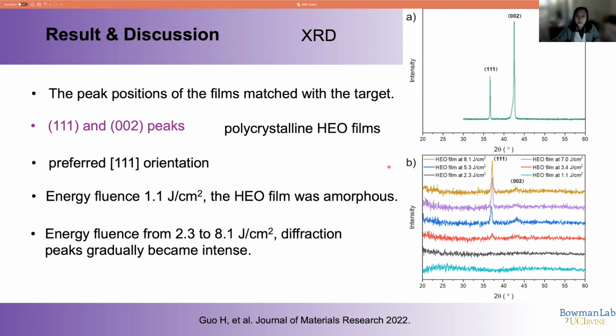phase. Next, we can see 111 and 002 peaks at the same time in the theta-2theta XRD spectrum of the HEO films. That means the films are polycrystalline films. Next, there is a preferred 111 orientation in our fabricated HEO films. For the target, the ratio of the intensity of 111 to the intensity of 002 is much lower than that in the thin films. In the thin films, the intensity of 111 is much higher than the intensity of 002.